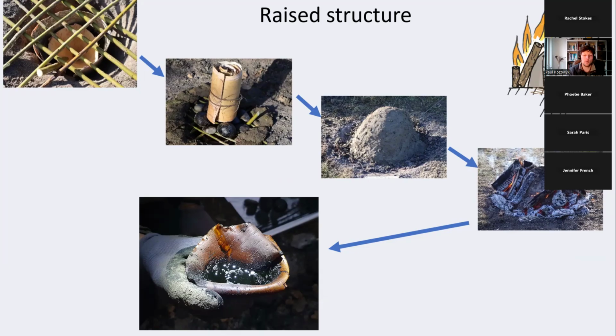is a pit in the ground with a larger birch bark cup. Then you light a fire all the way around this, let it burn for several hours, and the tar is formed inside the oven, which is excluding all the oxygen, and drips down into the cup below, and you get quite a large yield of tar from that technique. But it's something that takes quite a lot of planning and preparation, and then you can leave it alone as the fire burns for several hours.